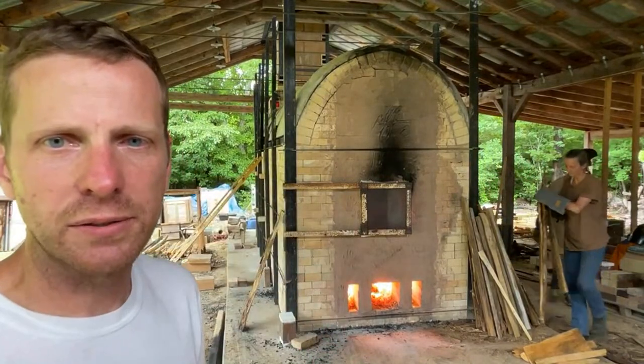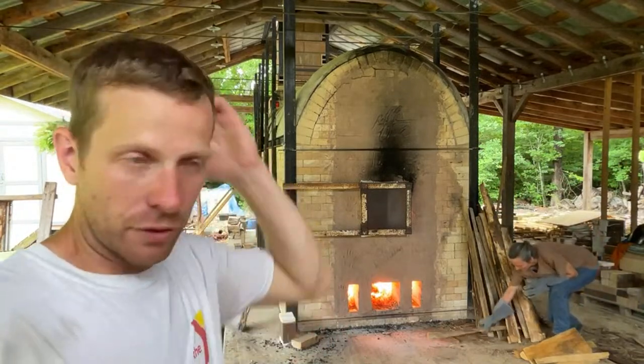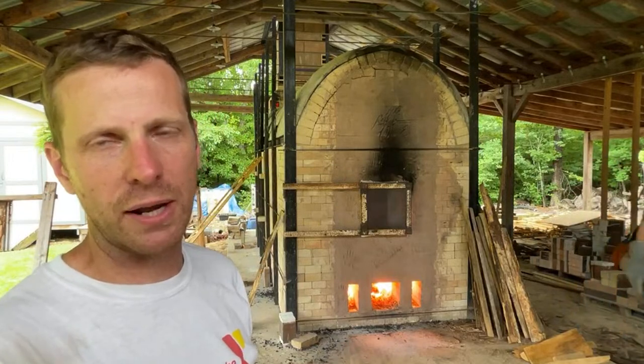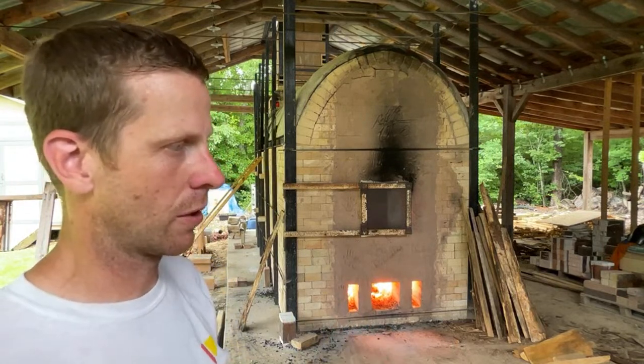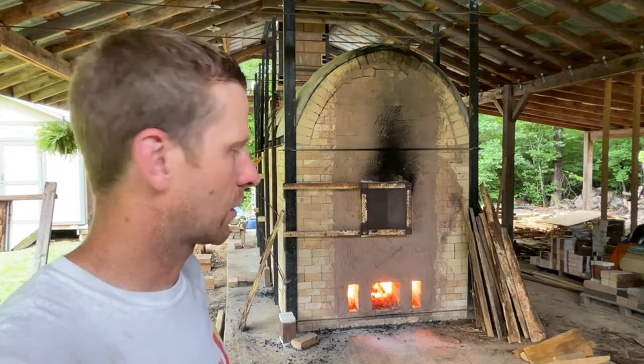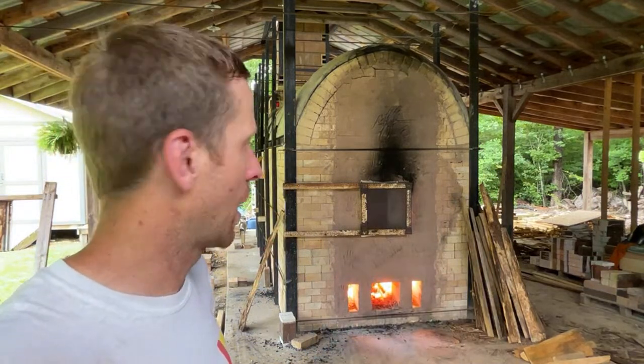What's the rest of the process after we're done salting? Pretty much we have to fire for a full hour after finishing the salting so that we can get all the excess salt burned out of the kiln so the atmosphere is clean, also remelt all the glazes if they've cooled down from introducing all the air and salt into the kiln. And by clearing out that atmosphere, all the glazes that should be shiny can, like I said, remelt and clear out the atmosphere.